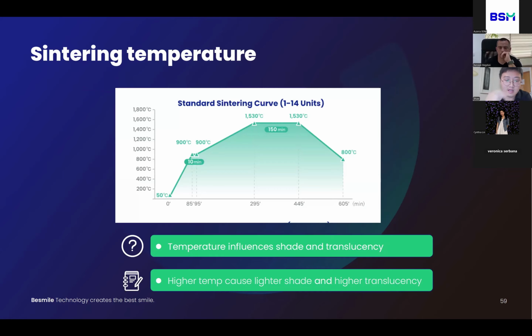Okay, and another factor that affects the shade and translucency is the sintering temperature. Generally speaking, high temperature causes a lighter shade and higher translucency. So if you want a lighter shade or higher translucency, you can increase the temperature by 20 degrees. If you want a darker shade, you can decrease the temperature by 20 degrees.